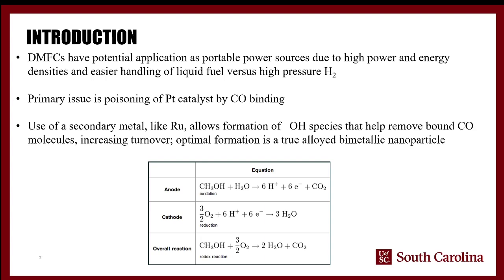And what that means is that if you wanted to imagine a straight line, you would have platinum, ruthenium, platinum, ruthenium, platinum, ruthenium, all the way through. And so by doing that, you would always have a platinum and ruthenium atom, the two separate active sites, sitting next to each other as neighbors. And so that minimizes the amount of energy that's required for those two coordinating reactions to happen. Your turnover is maximized, and you get the highest possible activity out of your catalyst.